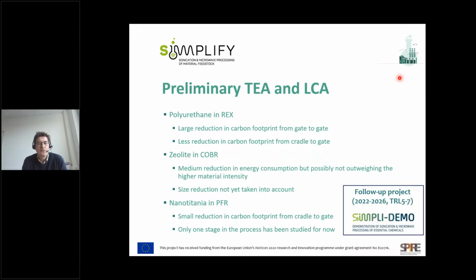Zeolites in the COBR, there we have somewhat lower reduction in the energy consumption, which is possibly not outweighing the higher material intensity that is needed. Although in this case, the deagglomeration by ultrasound, for example, is not yet taken into account, which will have an effect on the downstream processing, as was already also mentioned. This is important to take into account, as already mentioned by the other projects as well. In the nanotitania case, we only see a small reduction in the carbon footprint, but only one stage in the process has been studied. Calcination of the titania is being studied at this moment, but not yet from an LCA perspective, and we expect better improvements there.